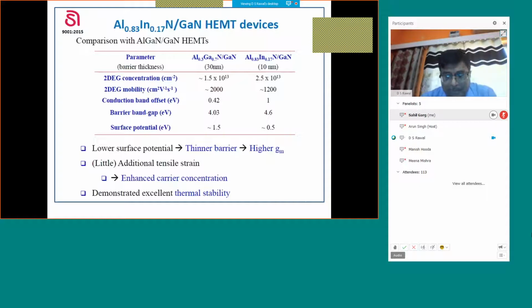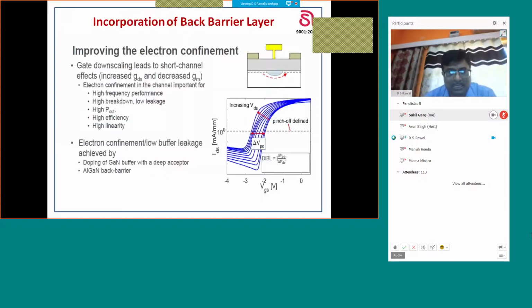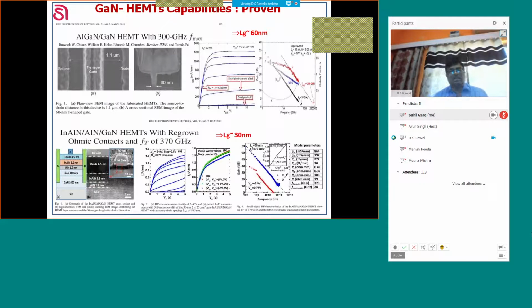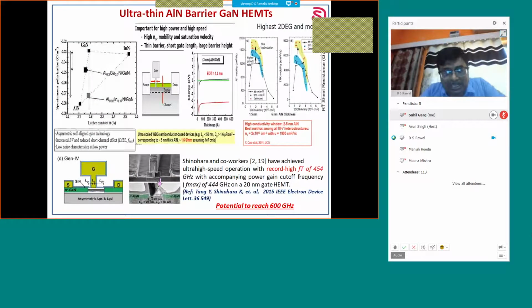These kinds of devices are preferred for high frequency applications, and you can see the GaN HEMT capabilities which have already been reported. The best GaN HEMT is reported based on an indium aluminum nitride/gallium nitride heterostructure with a gate length of 30 nanometer. This is basically using the advantage of high spontaneous polarization difference and smaller gate length, of course with improved source drain contact technology. And so far the highest reported frequency for these gallium nitride HEMTs is based on an aluminium nitride barrier layer over gallium nitride.